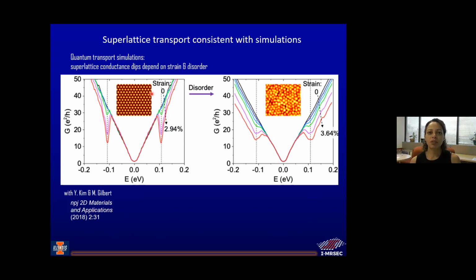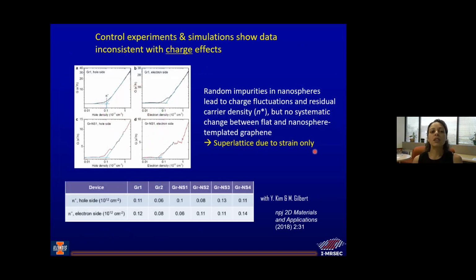group does really nice quantum transport simulations where they showed how the superlattice conductance changed as a function of strain and disorder. And you can see, for example, that for a perfectly ordered sample, you get these very deep secondary dips. But for a disordered sample, you can still see the dips in the way that we see them. So if we have more order, we could see clearer dips, but it's reasonable to see what we actually do. Okay. They also showed that the effects we see are inconsistent with charge effects, right? You do worry that there's random impurities that may be on top of the nanospheres, and that variation in potential can lead to what we see.